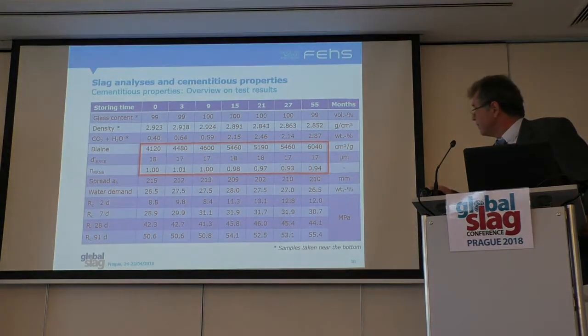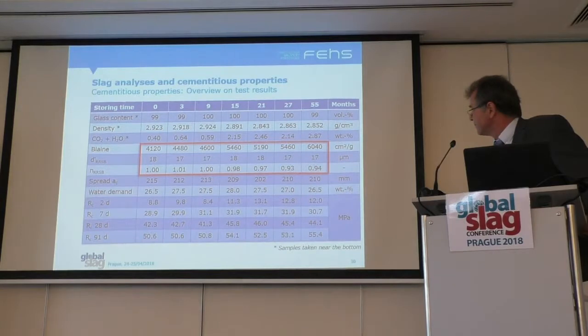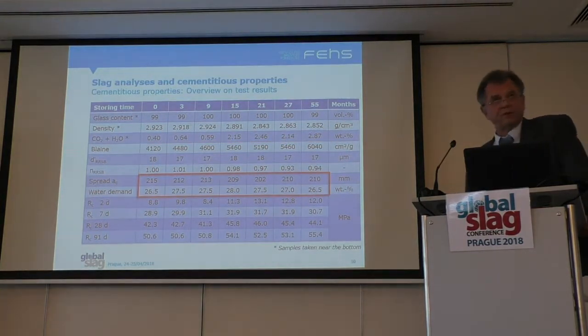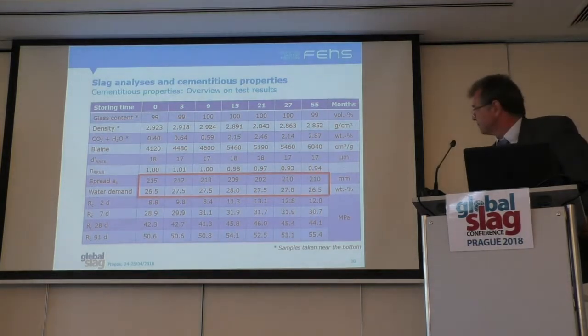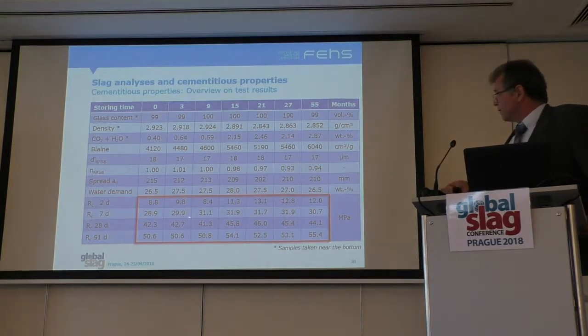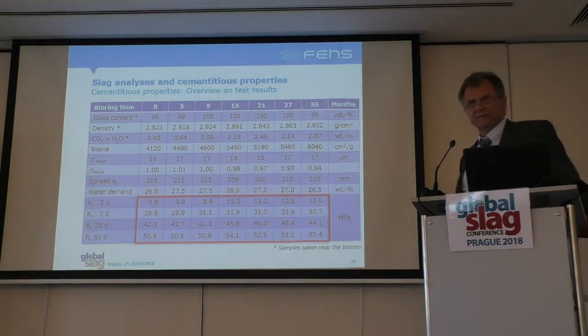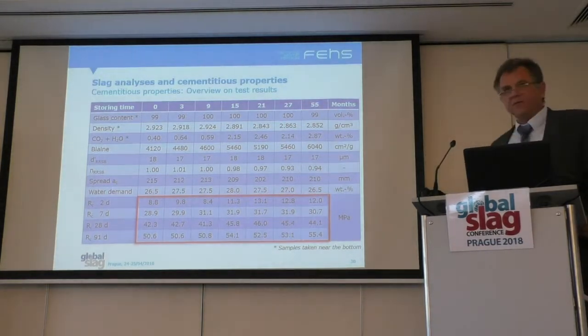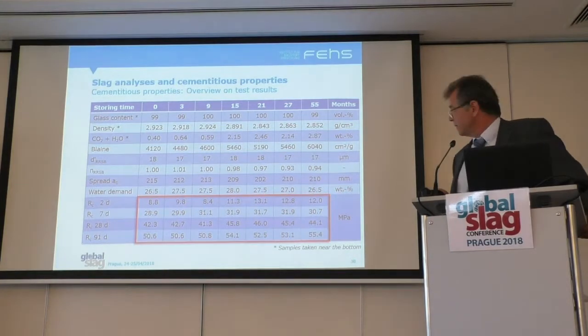Blaine value has nothing to do with the true fineness of the material. Workability of the mortars, in fact, not affected. Strength, we can see maybe a little bit higher early strength, but in any case we do not see a lower strength development.